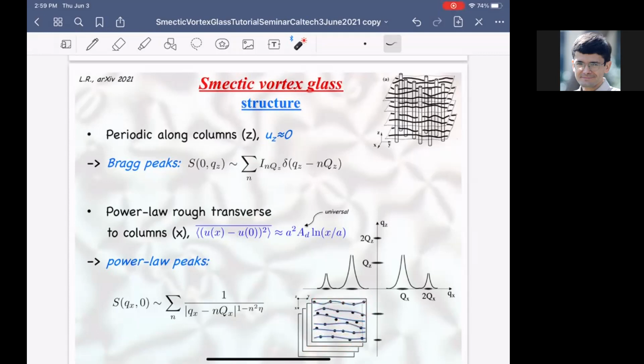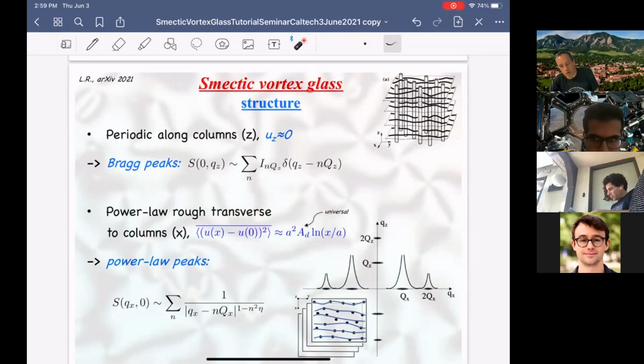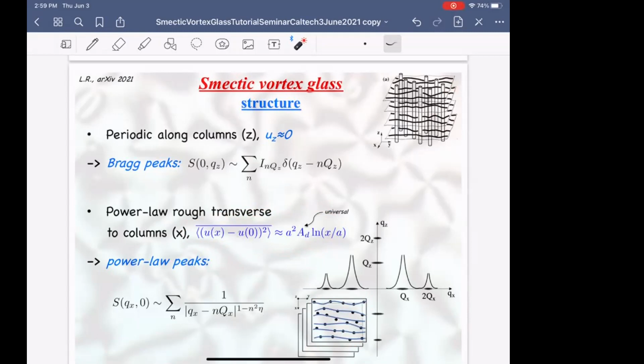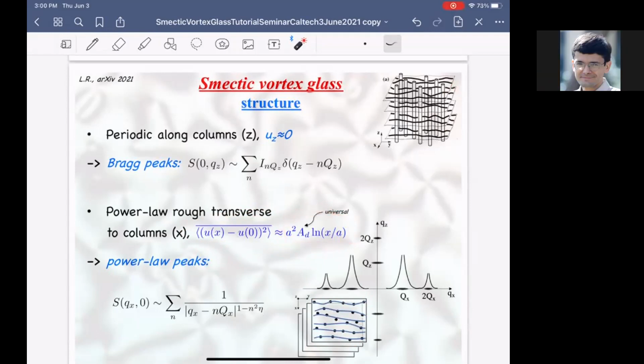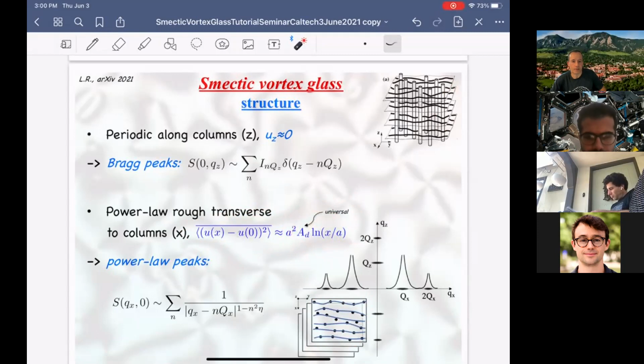So then it turns out, as I will describe if I get to it, that it's power law rough, and at least within the Bragg glass picture, you're getting Bragg glass-like logarithmic distortions with universal amplitude, A sub d. And correspondingly, if one looks at the structure function in the perpendicular direction, you get a power law structure function rather than delta functions. So it's a delta function in this direction, but it's a power law function with a universal exponent in the direction transverse to the columnar defect. So this is power law, but it's periodic in the z direction. Any questions about that structure?